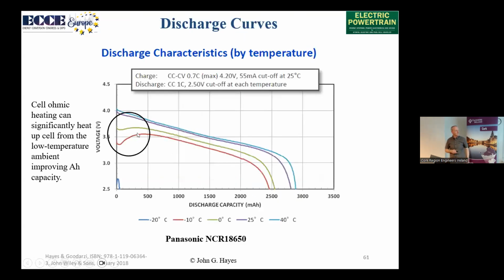Again, the Panasonic stuff is great. Panasonic are showing here a discharge of the pack at 40 degrees, 25 degrees, 0 degrees, -10 degrees in red, and -20 degrees in blue. So the pack resistance is really high. But we notice here, right? You notice this, that